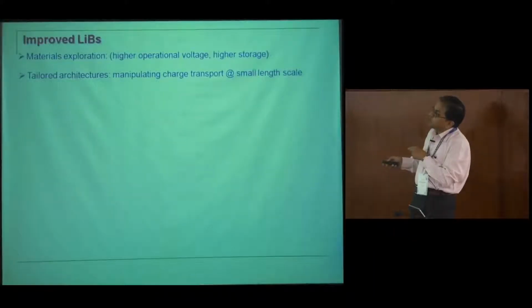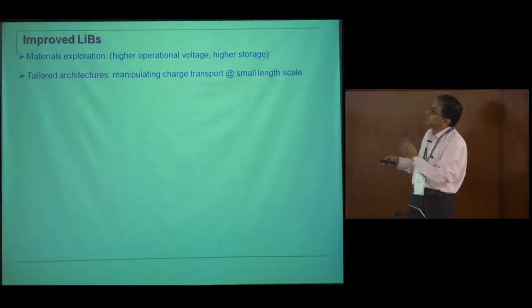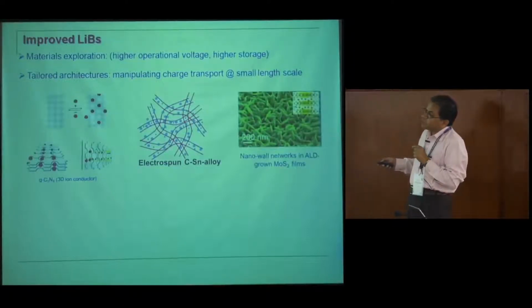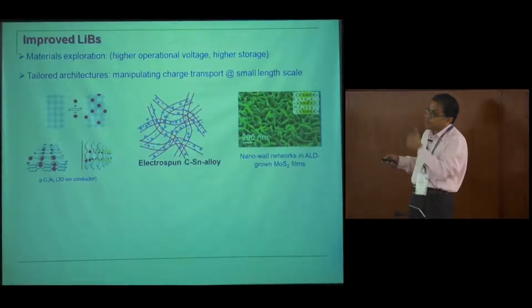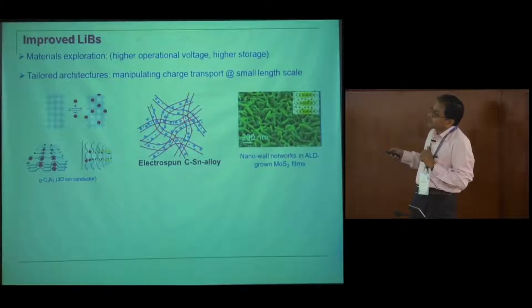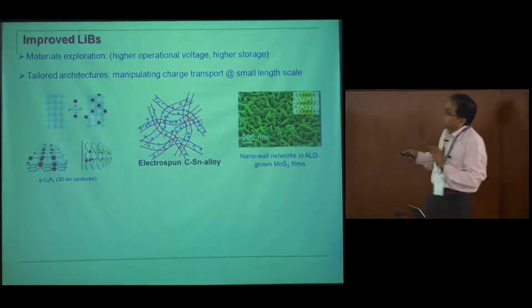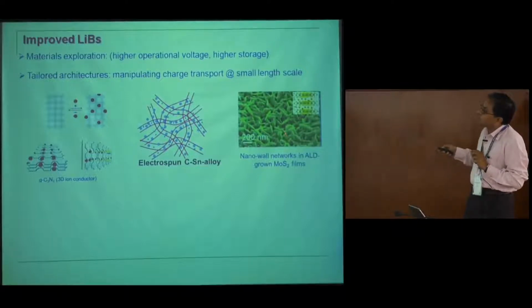Of course, this is some contribution we had this year, where we have a layered system which shows a mixture of both insertion and alloying chemistry in one compound. There have been ways of improving the architectures, typically controlling and manipulating the charge transport at small length scales, using graphene, specially architectured graphene, where you have transport even in the third direction. In addition to the two-dimensional transport, you have special architecture in the form of alloys being put inside a carbon fiber, or using very advanced techniques to grow thin films, where you're trying to manipulate the transfer through a network of nanowalls.